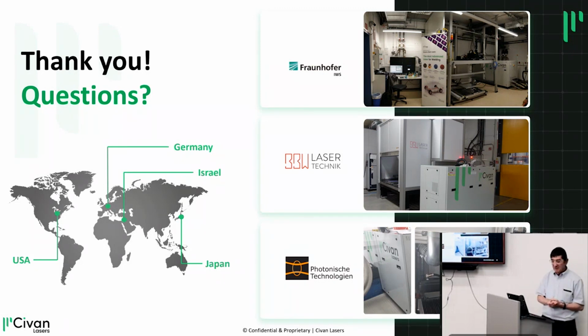We demonstrated that. When people go to picosecond and femtosecond, it already becomes more complex. But if you do this in nanosecond, you can get 30 or 100 times the peak energy than if you do it just with a single laser, and you get the dynamic beam. So the answer is in principle yes. We're not doing it right now.